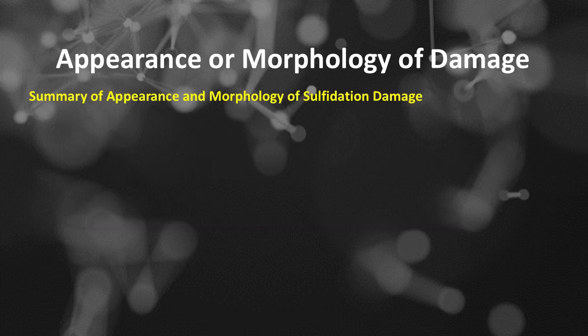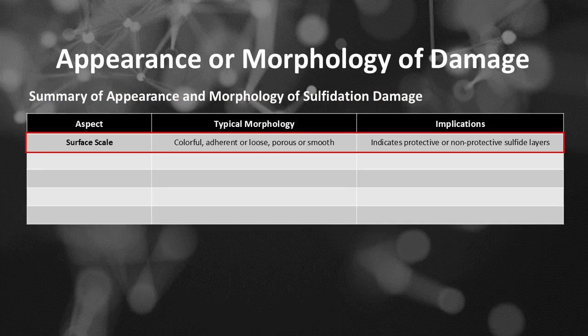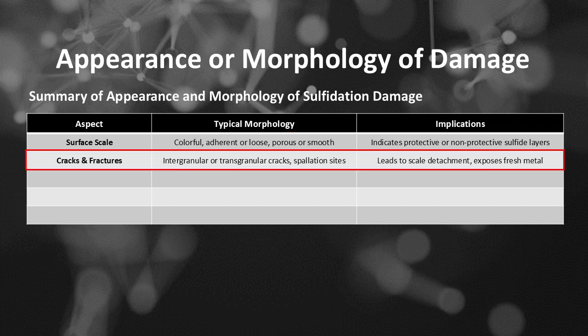Summary of appearance and morphology of sulfidation damage. If the aspect is surface scale, then typical morphology is colorful, adherent or loose, porous or smooth, and its implication is that it indicates protective or non-protective sulfide layers. If the aspect is cracks and fractures, then typical morphology is intergranular or transgranular cracks, spallation sites, and its implication is that it leads to scale detachment and exposes fresh metal.